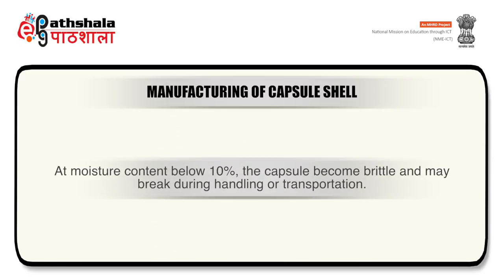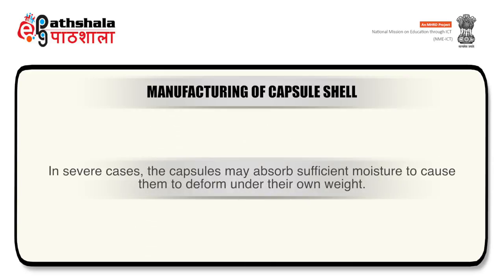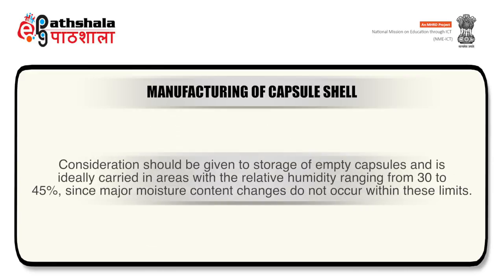The moisture content of the capsule is crucial for its mechanical strength, and moisture content from 12 to 15% is considered optimum. At moisture content below 10%, the capsule becomes brittle and may break during handling or transportation. At moisture content above 16%, the capsule loses its mechanical strength and becomes soft and tacky, and in severe cases may deform under its own weight. Storage of empty capsules should ideally be in areas with relative humidity ranging from 30 to 45%.